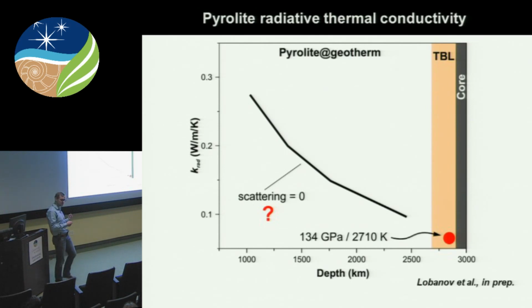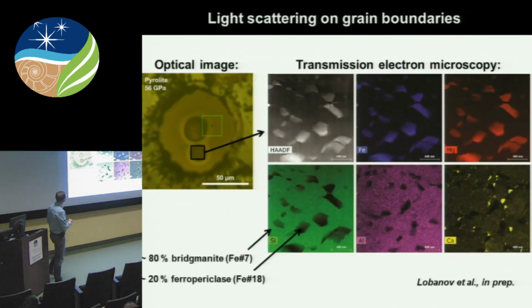So if we now run these spectra through the K-rad formula, we end up with a radiative conductivity dependence that is opposite in sign in its depth, in its slope, compared to the conventional models. So this model, however, also assumes zero scattering in the sample, but we actually can say something about the scattering effects. And here I'm just showing you an optical image of our pyrolite sample laser heated at 56 GPa.